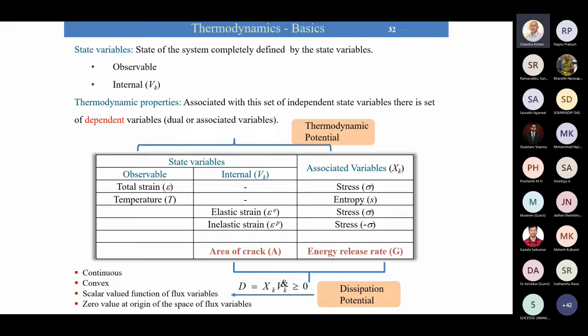So we define 2 potentials, thermodynamic potential and dissipation potential. This thermodynamic potential describes the elastic behavior, through which all the laws of linear elasticity can be obtained. This thermodynamic potential is a relationship between observable and the associated variables. On the other hand, we have the dissipation potential, which is a relationship between the internal and the associated variables. This is due to some kind of dissipation taking place, like friction, collisions, cracking, micro cracking, and so on. In our work, micro cracking takes place wherein a lot of energy is dissipated. So we can relate all these through a dissipation potential, and for the second law of thermodynamics to be applicable, this potential should be continuous, convex, scalar. So there are certain laws which have to be satisfied.